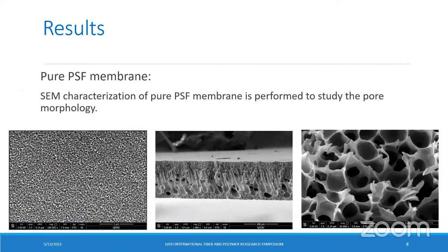So moving on to the results, scanning electron microscopy is usually used to visualize the pore morphology. We have used it to visualize the fabricated pure polysulfone and polysulfone PVP membranes. SEM is a very helpful tool in studying the porosity and pore size distribution of the membranes. We have used liquid nitrogen to obtain the cross-section of the membrane samples before their coating with a 5 nanometer gold layer. As for the pure polysulfone, here we can see the SEM images.